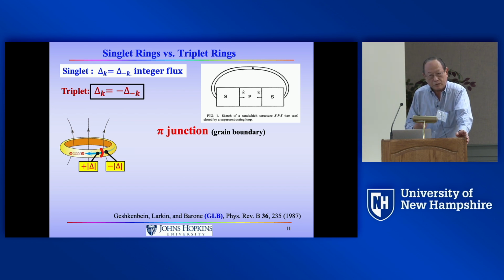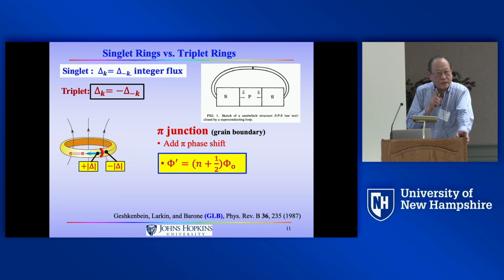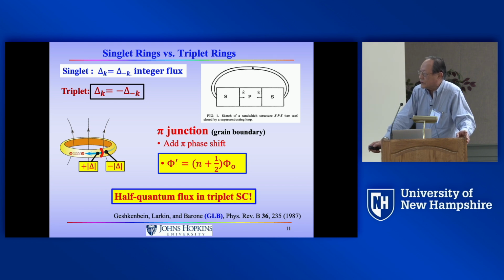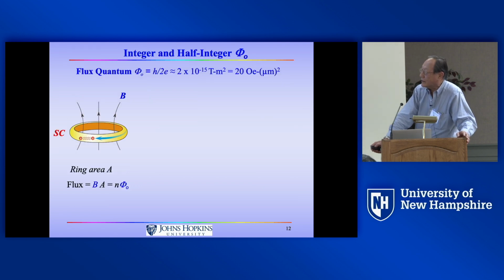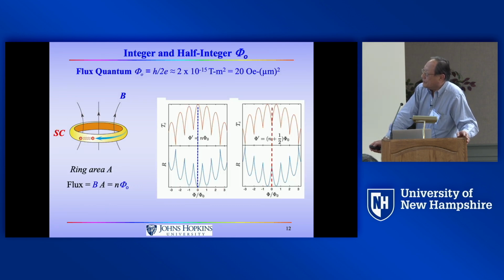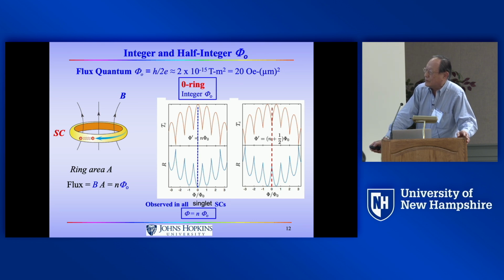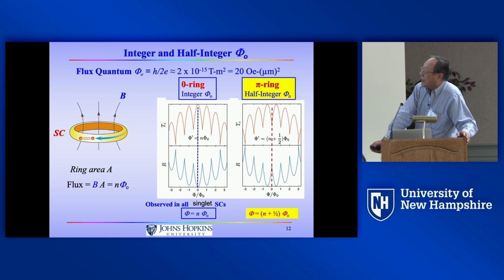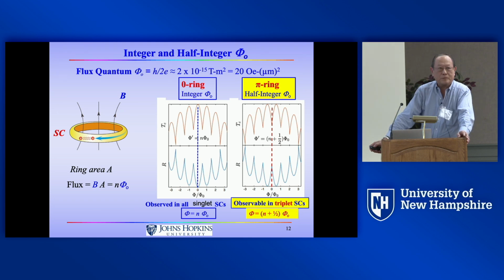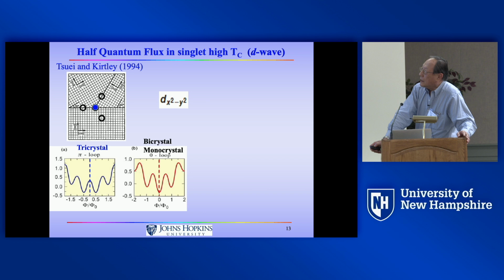Your external field must provide the rest so that you still have integer flux, so your oscillation will occur at half integers: 1/2, 3/2, 5/2. This will be the key evidence for a sign change in the gap value. This is why half quantum flux occurs in a triplet superconductor if you make the ring out of it. The integer, as I mentioned, is already observed in all the singlets. The half quantum should be observed in triplets, if you can find a triplet.